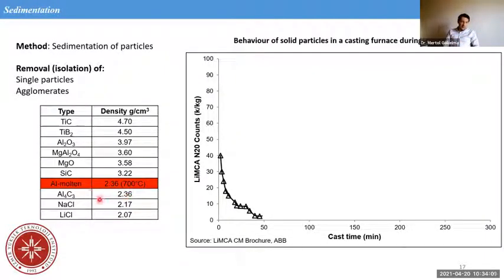So the carbide has a very similar density, as you see, but most of the inclusion densities are above aluminium, so that's why sedimentation actually works. This is a casting furnace, LIMCA measurements, online inclusion detection results. Here on the y-axis, we see the inclusion counts times 1,000, like 50 means 50,000 particles per 1 kilogram of aluminium. And first, when we add the melt or scrap, or whatever, it can be primary or secondary, sedimentation starts. So if you wait like 30, 40 minutes, the level of inclusions is quite low and is ready to cast. So they are isolated on the bottom of the furnace.